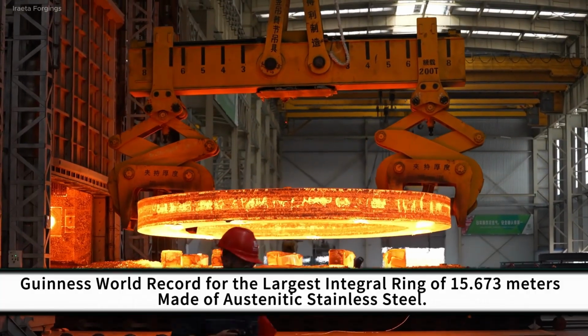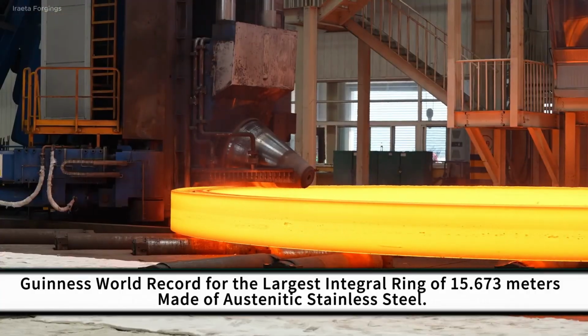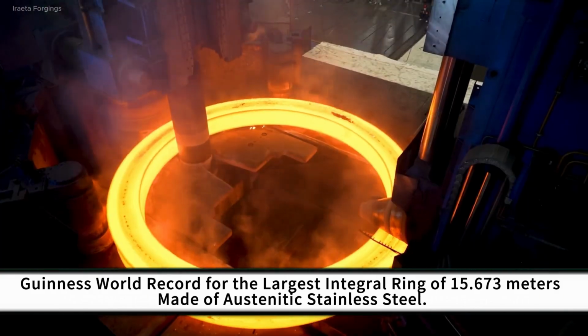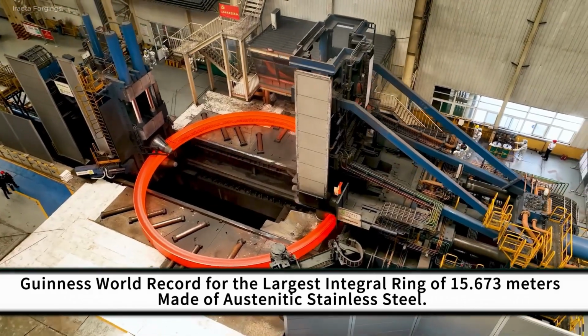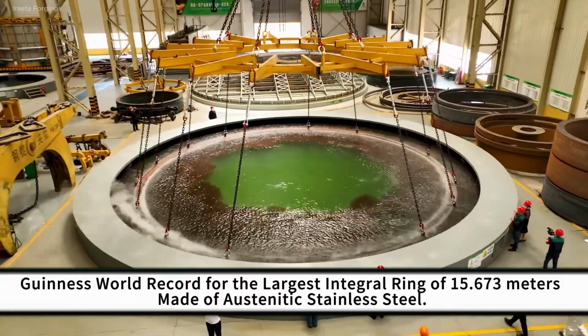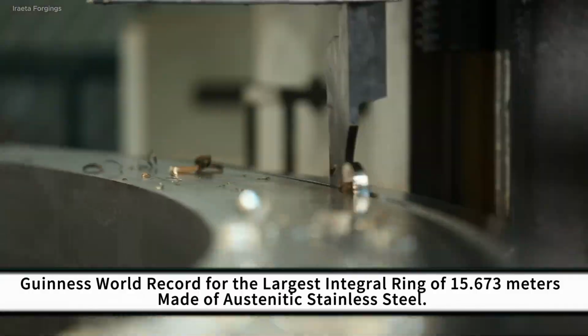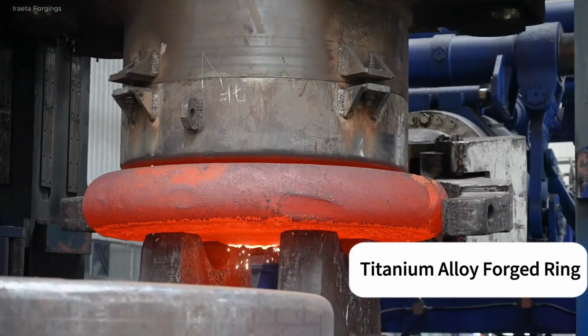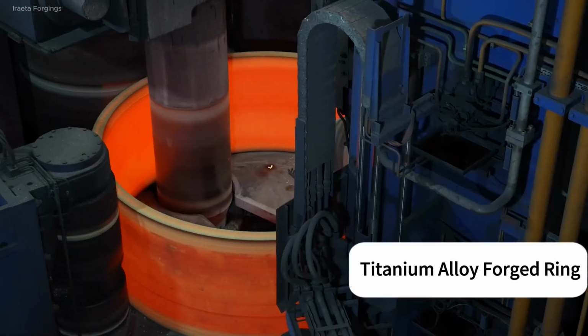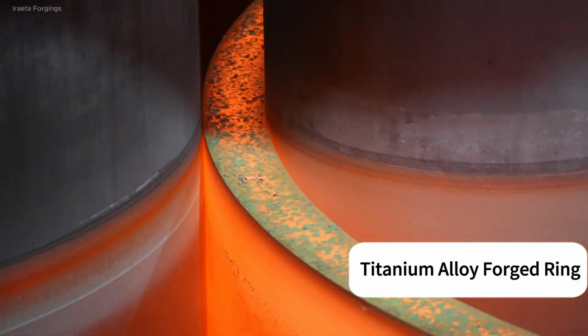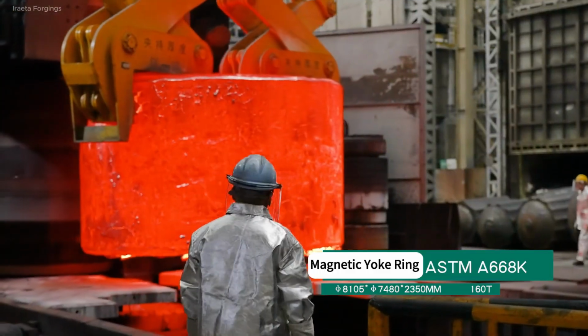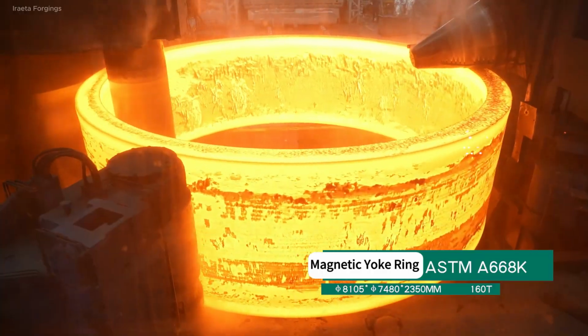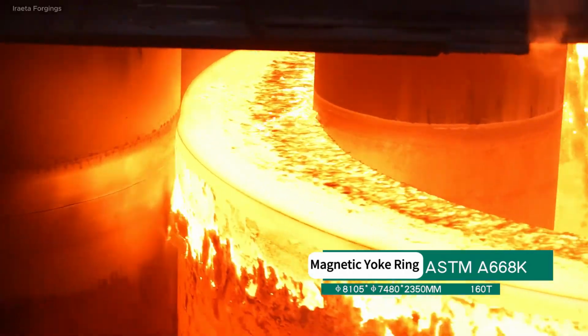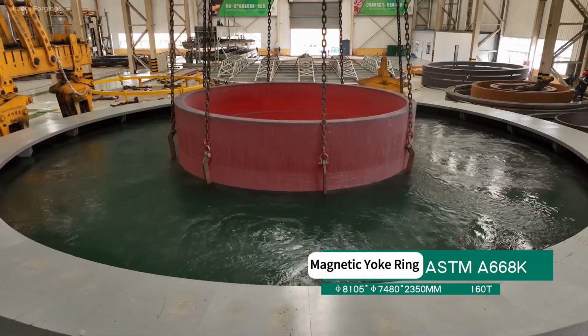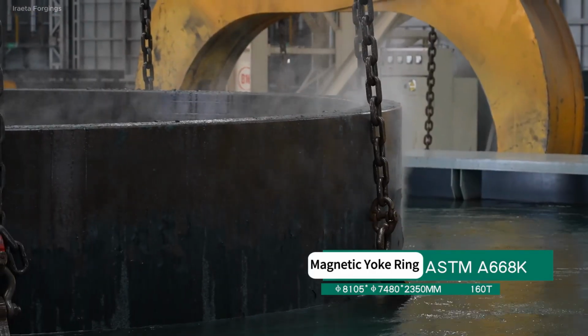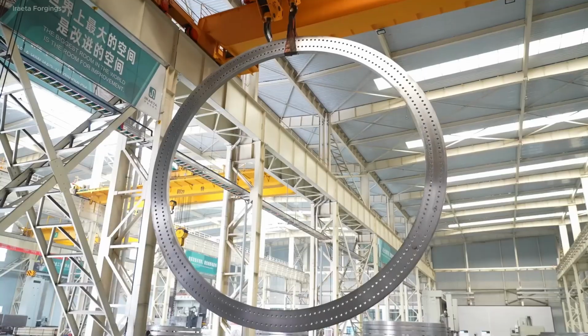The integral ring, made from steel, titanium alloy, and magnetic yoke rings, represents an extraordinary engineering achievement. It includes the Guinness World Record for the largest integral ring, measuring 15.673 meters, crafted from austenitic stainless steel. This titanium alloy forged ring, known as ASTM 668, is designed with dimensions of 8,105 millimeters by 7,480 millimeters by 2,350 millimeters and weighs 160 tons. It demonstrates the advanced material science and precision forging technology used in creating massive structural components.